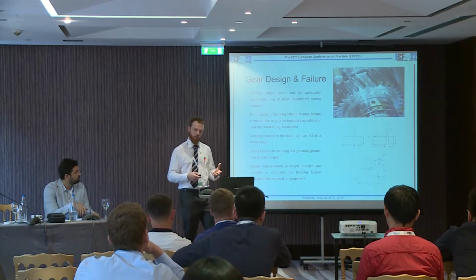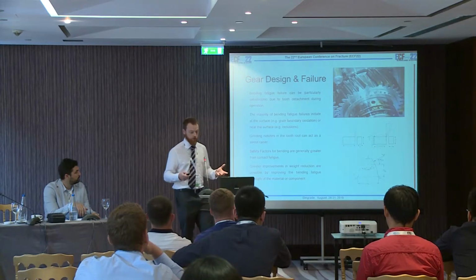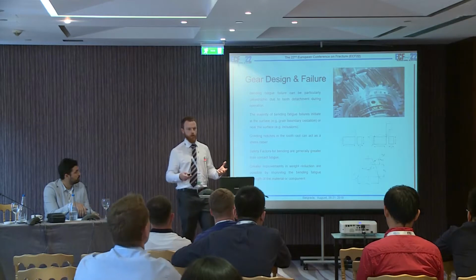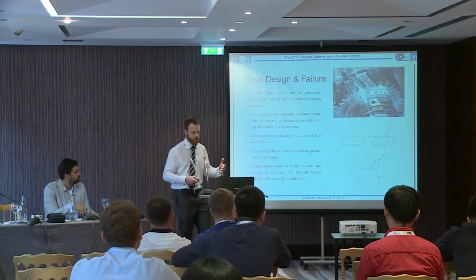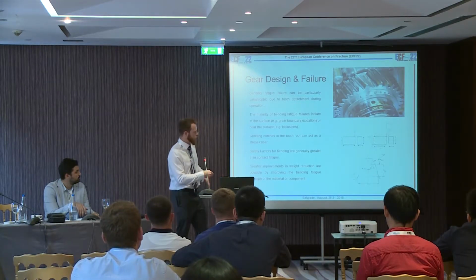Because it's such a catastrophic failure mode, the safety factors are higher than in other failure modes. So therefore, you can see we've got a greater opportunity to reduce weight by increasing the bending fatigue strength. And just to quickly describe the actual failure mechanism, essentially we treat the tooth as a small cantilever.